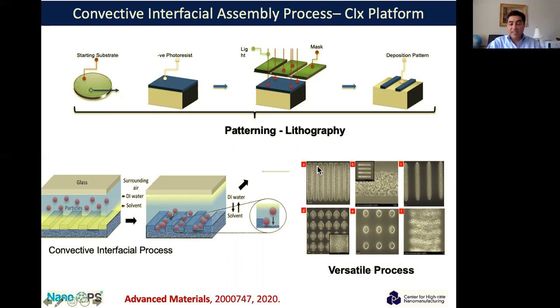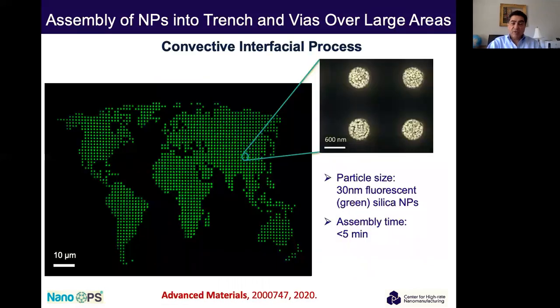And you can see some of the examples here. For example, you can make all kinds of structures using this technique. And it's a very fast technique. You don't need anything but the feature structure and some IPA and your ink solution. And so one of our students did a map of the world using dots. These dots are about 500 nanometers, or between 400 and 500 nanometers. And these particles are 30 nanometer particles and they're fluorescent particles. And you can see the assembly time in this case was 5 minutes.